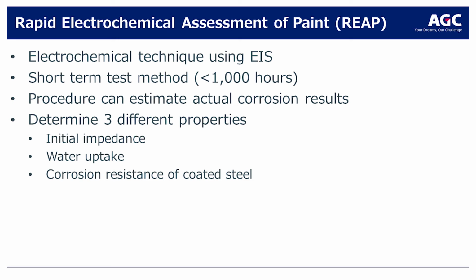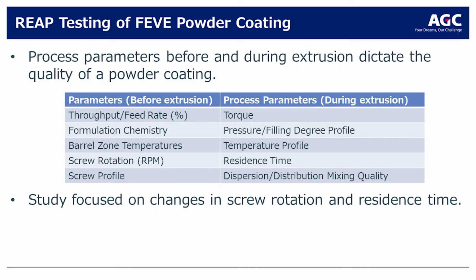There's another technique we can use called rapid electrochemical assessment of paint, REAP, using EIS. This is a short-term test, and you can estimate corrosion results. You can get initial impedance, you can get water uptake, and the corrosion resistance of the coated steel. We did this on a powder coating initially, because you'll see in the next slide the powder coatings have some properties that make the contrast between a good coating and a not so good coating a little bit easier to see.